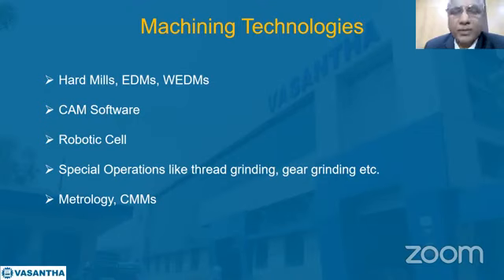When I say inserts, some of you may not be aware, but people from the field would be. When we make a high cavity mold, each cavity or two cavities will have one insert. Those small parts are called inserts, especially for high cavity molds for smaller parts. These inserts need to be in hardened condition, at 50 HRC. The class 101 classification means that inserts need to be hardened to 52 HRC, and they have to be at least H13 hot die steel, or the high chromium steels like Stavax and Mirax, which are brand names from Uddeholm.